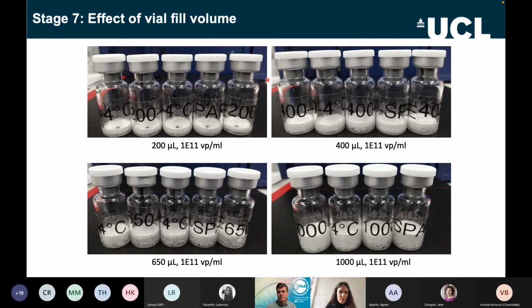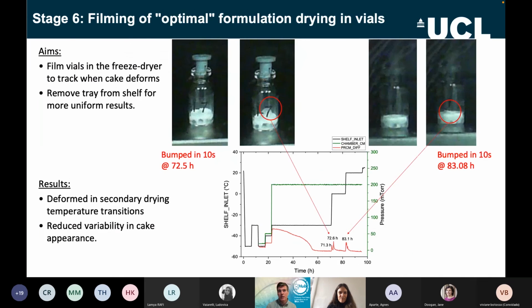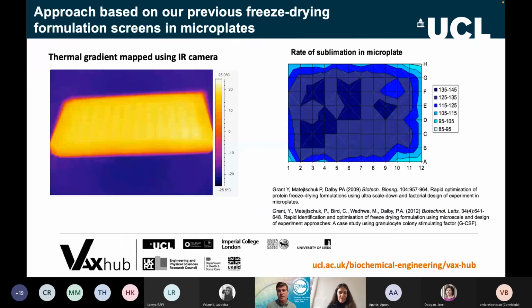Can't see any more questions at the moment here, so I think thank you very. Oh, hang on, there's another one, Paul. Even though thermal mapping showed even temperatures across the plate, why did sublimation vary? Yeah, so that's due to a vapor pressure issue. So if you imagine you've got your plate, remember what you're doing is you're removing water, and it forms like a vapor layer in the chamber, which is being removed. You have an escape route out of the freeze dryer. But if the vapor pressure is building up over the plate, then it's more likely to build up over the middle than it is around the edges where there's no water vapor being produced. So you get this edge effect.